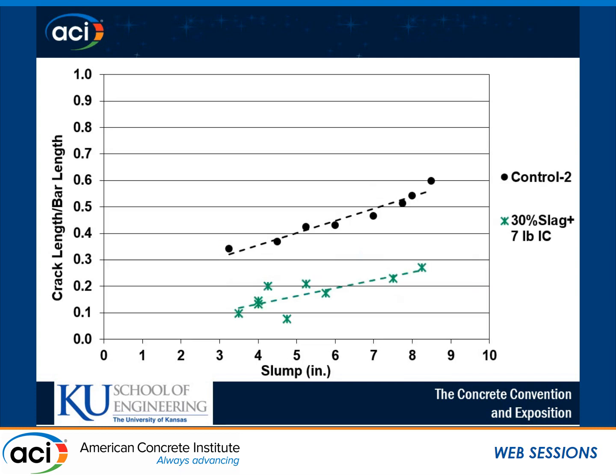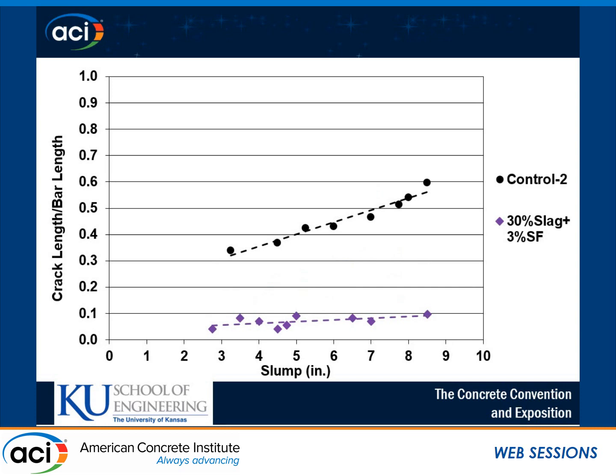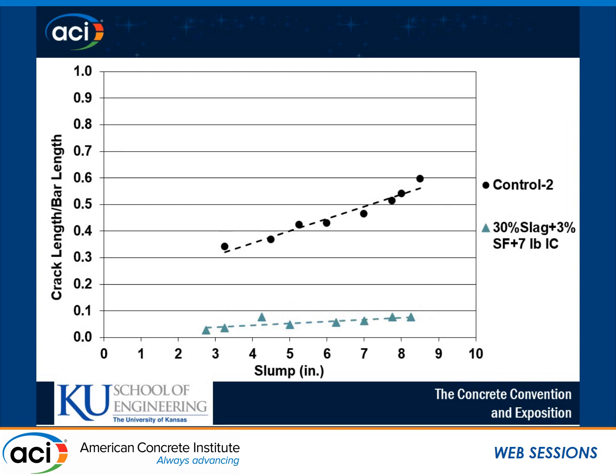And when we add 7 pounds per hundredweight of internal curing water, we see an additional reduction in settlement cracking at a given slump. And we see a significant reduction when we have a ternary mix. So with 30% slag, 3% silica fume, this is getting towards the limitations of our tests with, on average, less than 1 inch of settlement cracking per specimen.